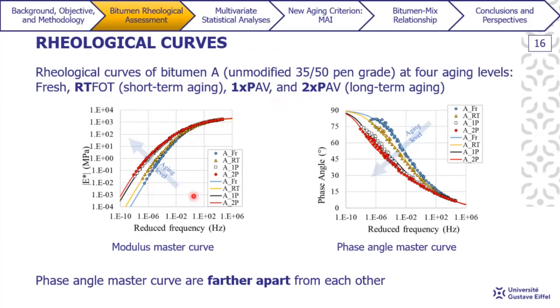Throughout this presentation. Here, what we can see is an increase in modulus that can mainly be observed at this region of low reduced frequencies. Whereas for the phase angle master curve, from a graphic point of view, we can see that the curves seem to be farther apart from each other when compared to the modulus curve, which helps us highlight the difference between each aging level.